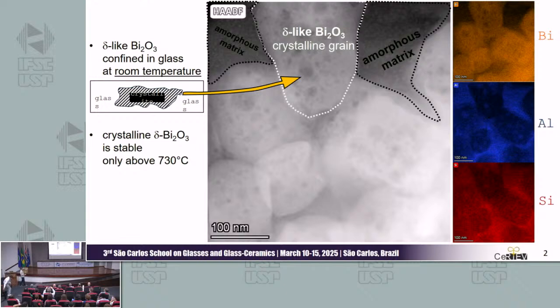Okay, so that is glass ceramics based on bismuth, silicon, aluminum oxide glasses. And what you can see in this transmission electron microscopy image is a crystalline grain embedded in amorphous matrix. What is interesting is that this crystalline grain is made of delta-like bismuth oxide phase, which normally is stable above 730 degrees Celsius. I have few working hypotheses why it is stabilized down to room temperature in glass ceramics, and